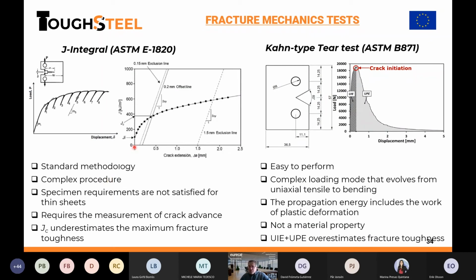The problem for these specimens is the loading mode, because after the crack starts to grow, the specimen starts to buckle at the crack tip, starts to have bending and compression here. So after a given point, the results we get with these specimens are not really related to the fracture propagation, because they also include compression and plasticity associated with the specimen geometry. So initiation, I think, is something we can rely on. You will see in the coming slides.